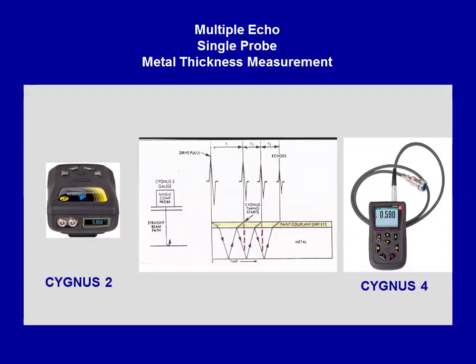We then look at the second echo, we look at the third echo, and we match the timings between the second and third echoes. When they match, and they must match exactly, then the instrument will display a measurement. What it's doing at that stage is verifying that the sound came from the same backwall reflector. And the measurement you get is an honest to God, accurate, verified, true, take it to the bank thickness measurement.